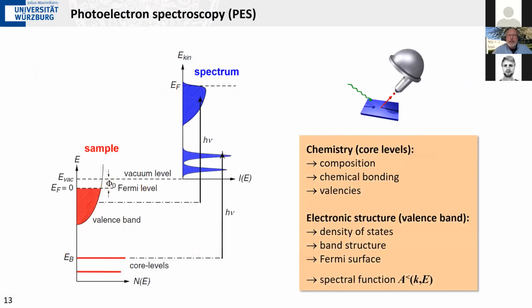Okay, so that's in a nutshell the most important message. What we can measure with photoelectron spectroscopy is chemical and electronic information. From the chemistry, we can learn about the elemental composition. We can learn about the precise chemical bonding and the valencies of the atoms in our compound. And concerning electronic structure, that is the information about the valence band, we can measure the density of states. But we can also, as we will see a little later, measure momentum information. So we can really map out the band structure, look at the shape of the Fermi surfaces, and that becomes also very important for transition metal oxides.